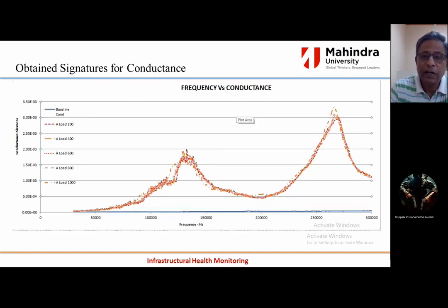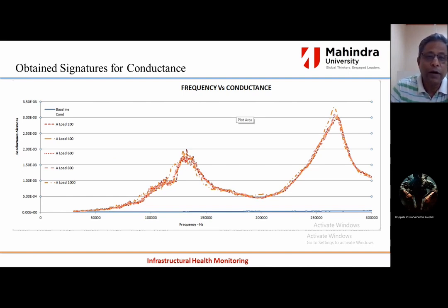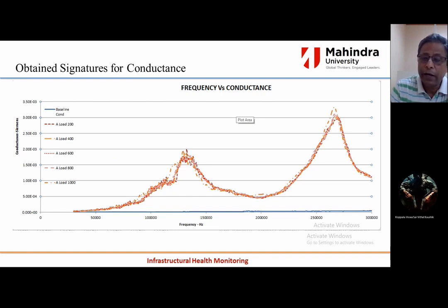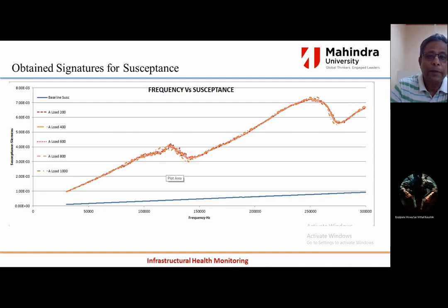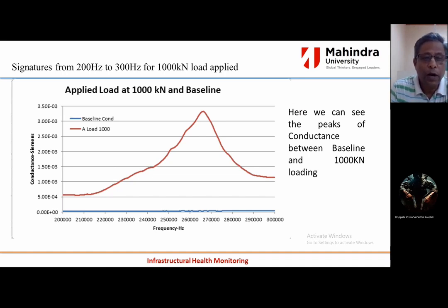This is the frequency versus conductance curve, showing the baseline compared to signatures at 200, 400, 600, 800, and 1000 kN. The curves are showing values nearly close together because the major damage occurred at 200 kN; after 200 kN there is not much additional damage, as the loading capacity is 1320 kN. This is also the susceptance signature curve.